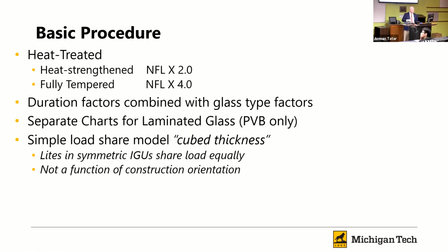After we have our non-factored load, then we would use factors to address heat treatments, also load duration. We have separate charts for laminated glass because the presence of that inner layer changes the way the stresses pass through the thickness of the glass. And then we have a relatively simple model to deal with load sharing between our two pieces of glass, or three, depending on if it's a double or triple insulating glass unit.